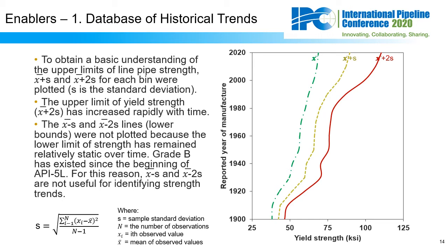Now one way that this plot could be used is if you walk up to an unknown pipe and do your NDE and discover that the pipe has an estimated yield strength of about 75 KSI, you can be relatively certain that this is a more modern steel and not one of these vintage steels that would tend to have a lower yield strength. But we wouldn't make conclusions based on one type of data if we have other data available, so it's highly preferable to use the composition data as well. So we'll demonstrate that process using manganese and sulfur now.